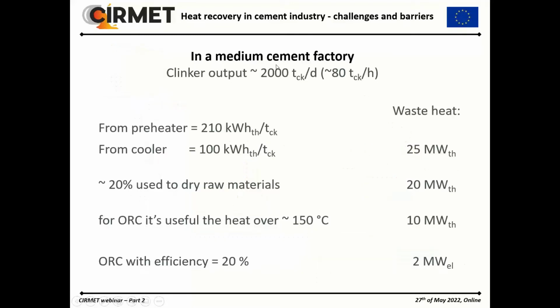In a medium cement factory with an output of 2,000 tons of clinker per day, we obtain 310 kilowatt-hour per ton of clinker. So it means a waste heat of about 25 megawatt thermal. 20% of them are used to dry raw material. We are left with 20 megawatt. The heat useful for the ORC is up to 150 degrees, so it remains about 10 megawatt. With an efficiency of 20%, we obtain 2 megawatt electrical.